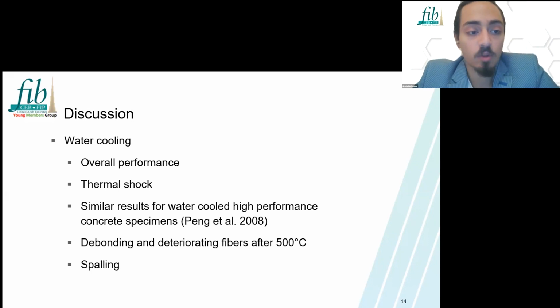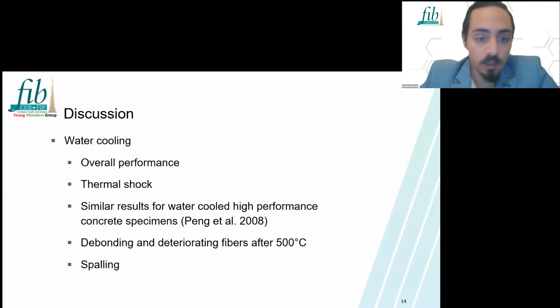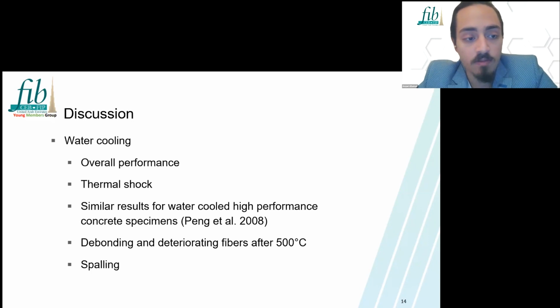Now, the steel fiber lightweight concrete was always better in terms of strength than lightweight concrete at every temperature, even for water cooling, since the fibers are able to improve the flexural strength because of their tensile nature. Moreover, in this type of water cooling, spalling was more of an issue than in natural cooling, because here you have different effects. For example, you have the steel fiber elongation at moderate temperatures, 400, 500 degrees. You have the thermal shock.